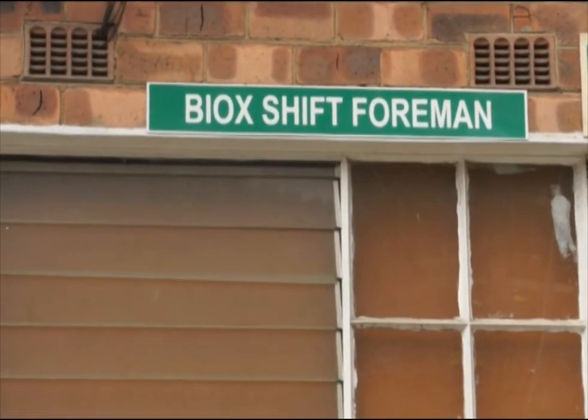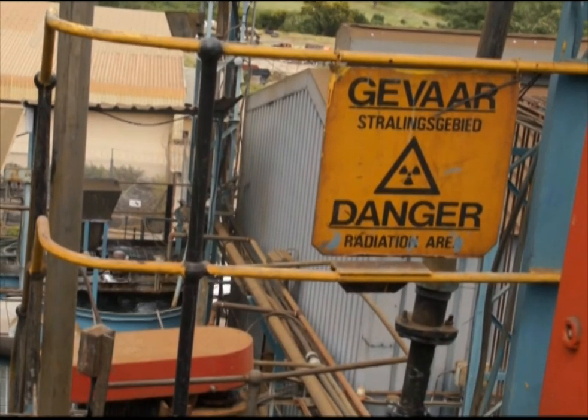The technology has already been applied successfully in other parts of the world. It's a bio-hydro-metallurgical process for recovery of refractory gold, or gold locked in sulphur minerals. The gold is very fine and it's in pyrite, and that means cyanide just can't expose the gold in order to recover it.